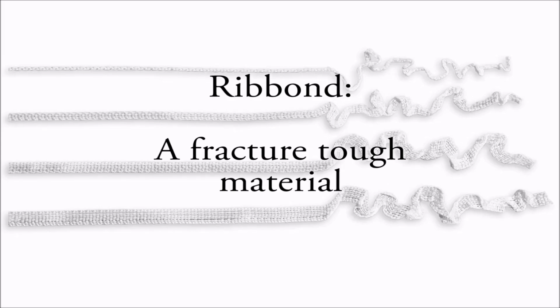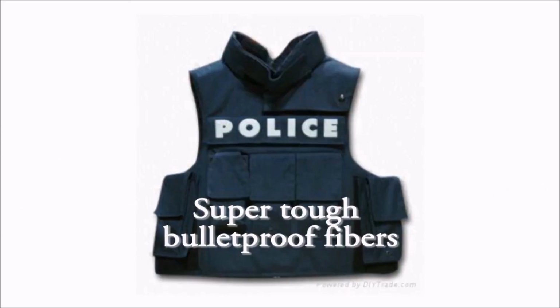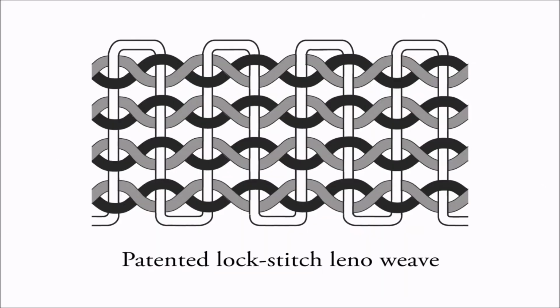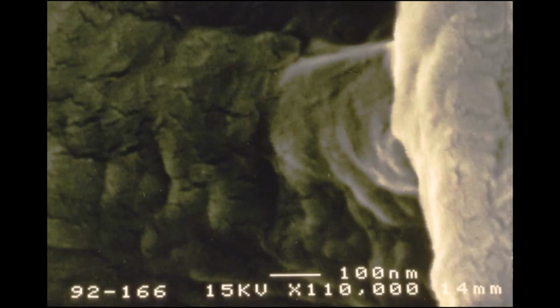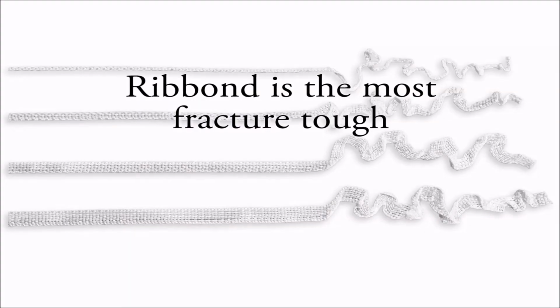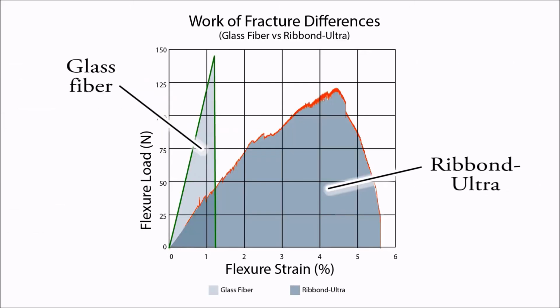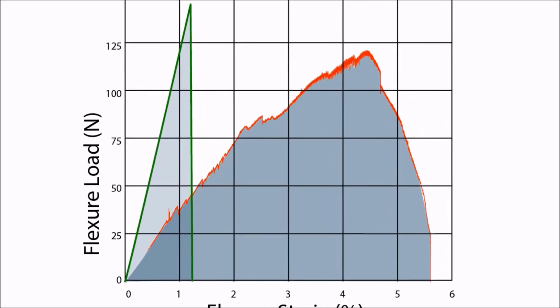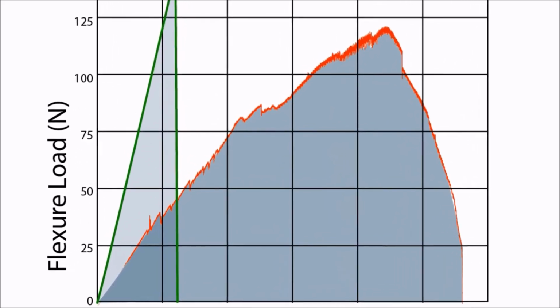The unique combination of Ribbond's super tough bulletproof fibers, patented lock-stitch Leno weave, and bondability characteristics make Ribbond the most fracture-tough fiber reinforcement available to the dental industry. This chart demonstrates the fracture toughness of Ribbond versus a glass fiber reinforcement. Fracture toughness is measured in these charts by the gross area under the curves. Although a glass fiber reinforcement might have higher flexural strength, you can see how the gross area under the glass fiber curve is significantly less than the curve under the Ribbond.